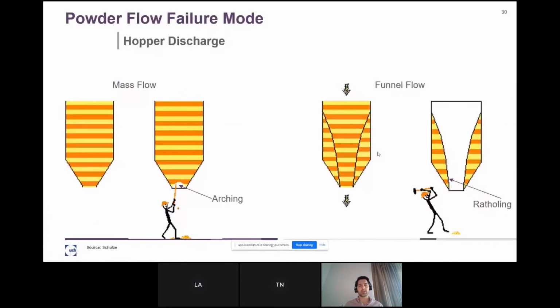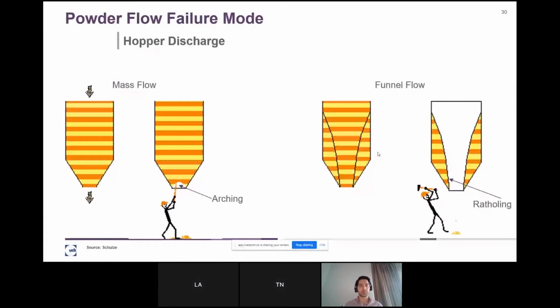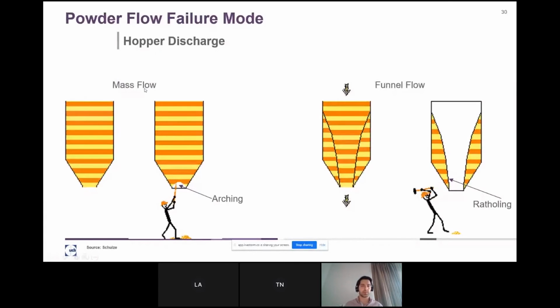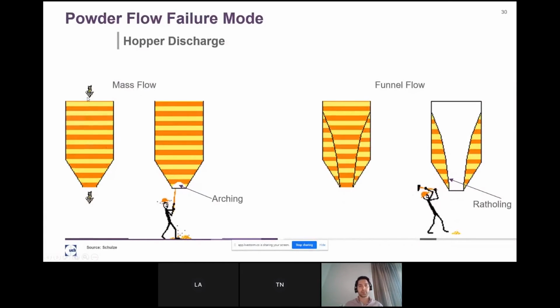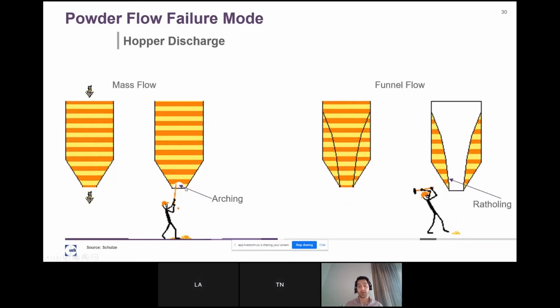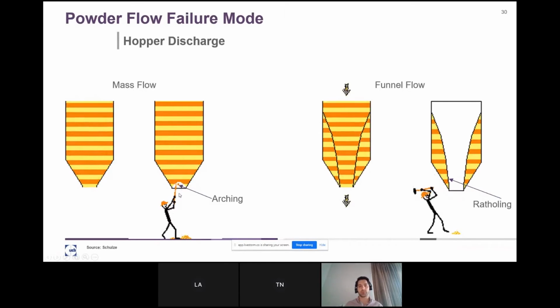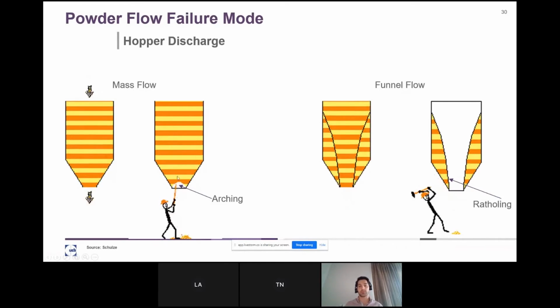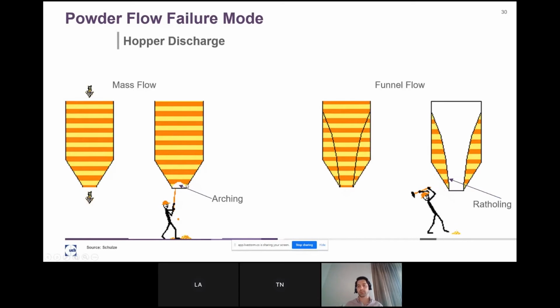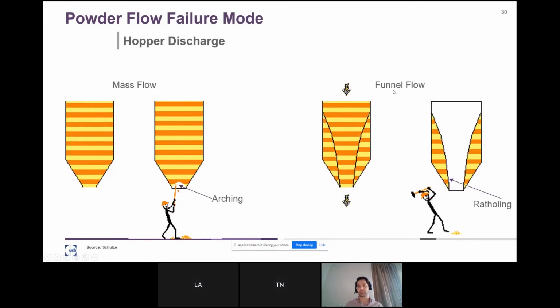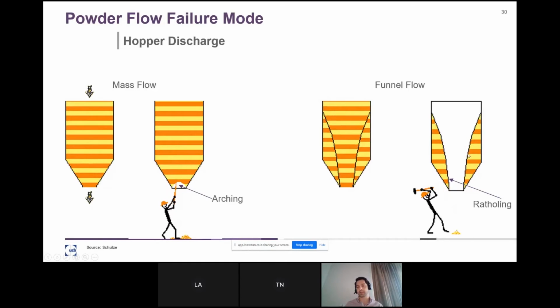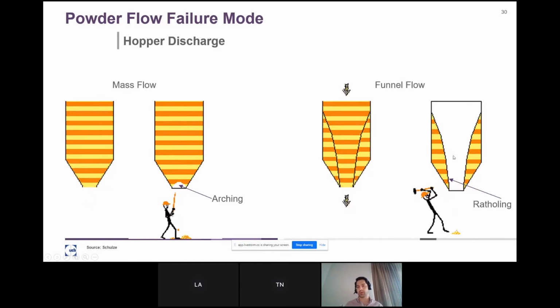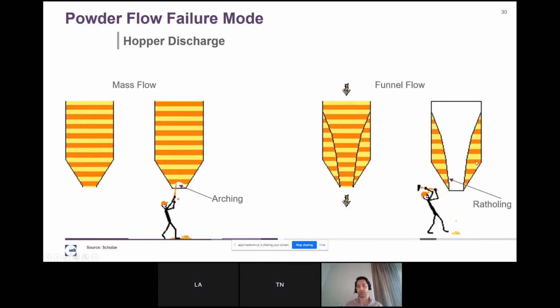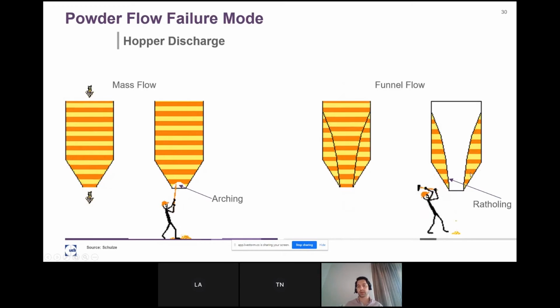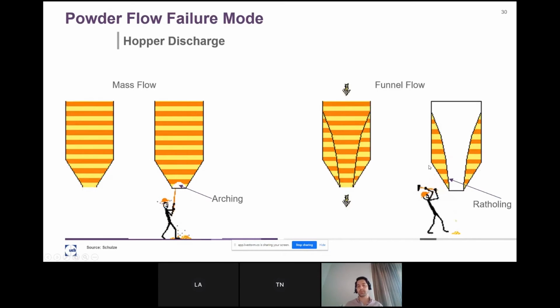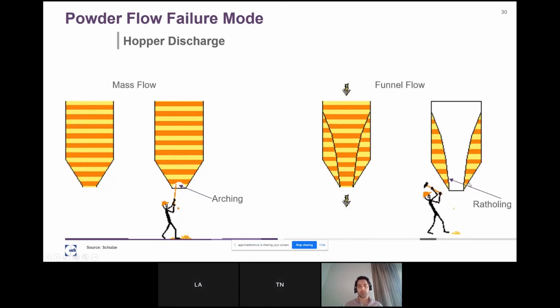Also, in terms of powder flow issues, this is one of the examples of the hoppers that I mentioned. In the hopper, as the powder flows out, you might form an arch, so there are no particles or powder going out. You need to disturb the neck here to let the powder go out. Or in some cases, you could have funnel flow or rat holing forming, when some of the powder stays close to the walls and doesn't come out. So you need to, again, apply a mechanical shock in order to remove it.